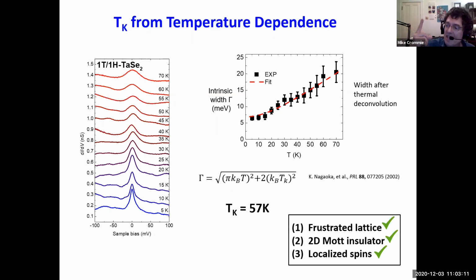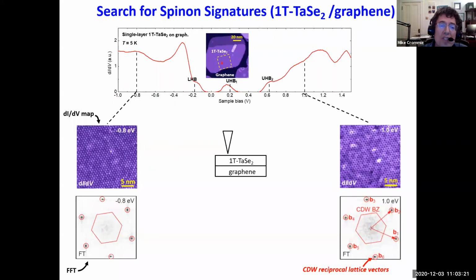We get a frustrated lattice, a 2D Mott insulator, and localized spins. And so now we're ready to go searching for quantum spin liquid behavior. We've satisfied all of these criteria. And so to search for signatures of the quantum spin liquid, what we did was very careful dI/dV maps at different energies in our material.